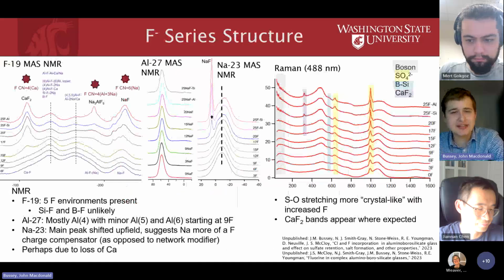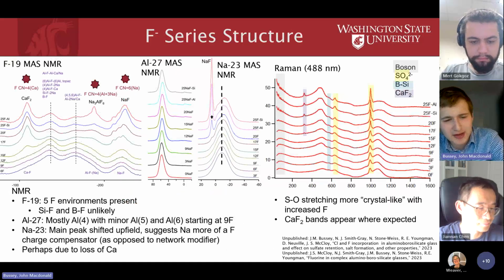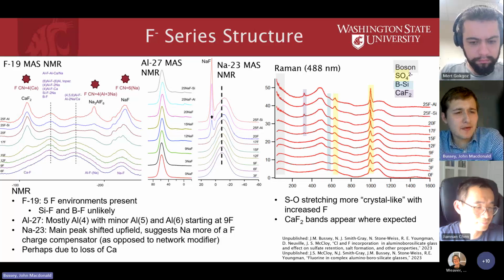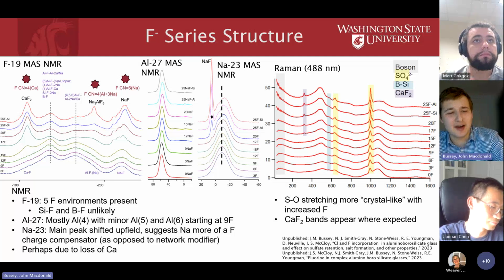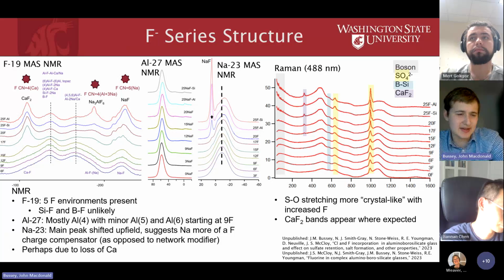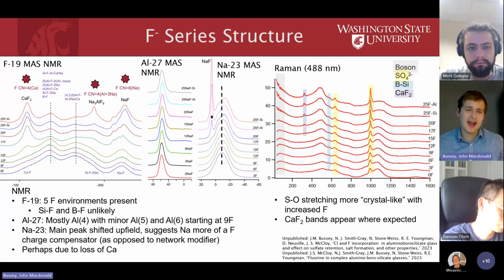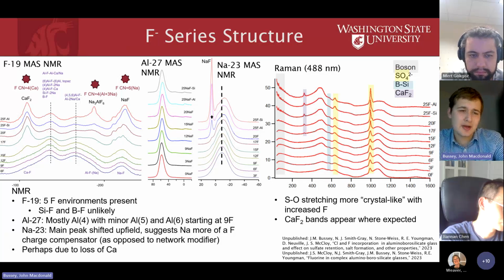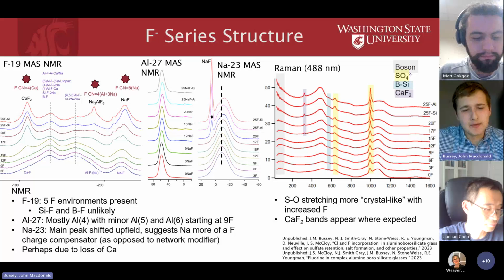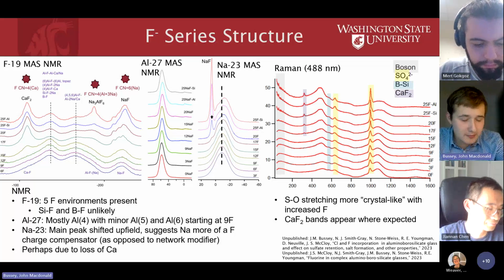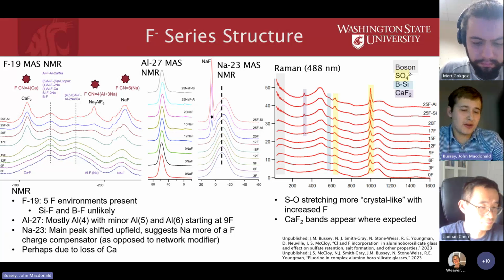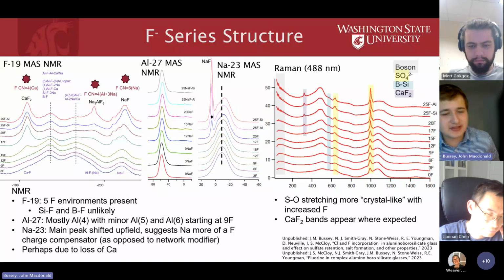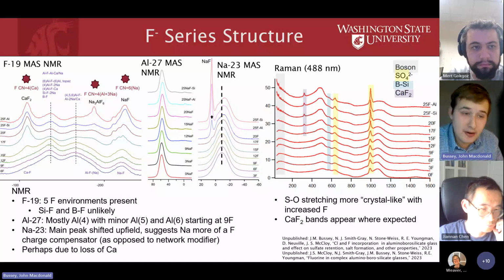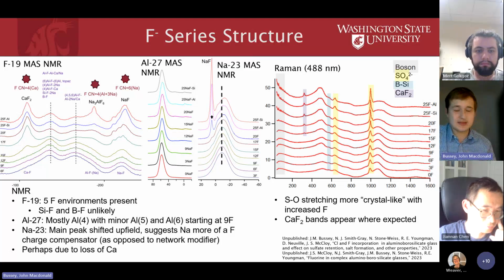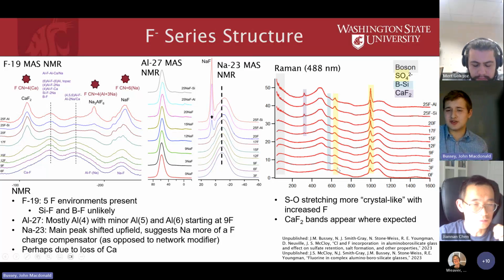So that makes some sense. Then, taking a look at the structure, these glasses were much more complex. Looking at the fluorine NMR, this is from an entire paper my advisor wrote on a separate subject, but basically it looks like we can assign five different environments. So the fluorine, once it gets in the glass, wants to be with calcium, but it also appears to be relatively happy in a glassy structure with aluminum and sodium as well. We also looked at aluminum-27 NMR, which indicated that the aluminum was almost always four coordinated. However, when we started adding more fluorine, we saw the presence of some five and six coordinated aluminum, and that corresponds to the aluminum in the glass as well as the crystal. The other thing to note here is looking at the Raman.